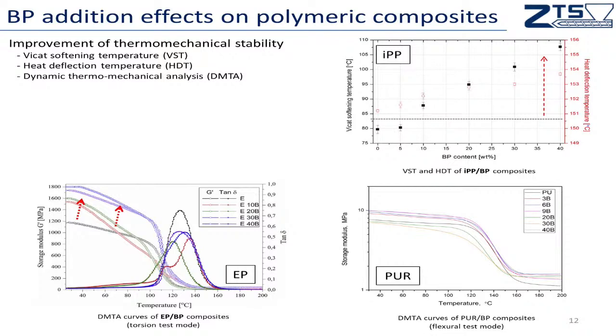The same phenomenon can be observed for the epoxy composites shown in the left bottom part of the slide. So we can see here the DMA curves of the epoxy resin composites. In the case of the highly porous structures of the polyurethane, the storage modulus, so the stiffness modulus, was improved by incorporation of the fillers. So for all materials, this is the property that will always change, and the same phenomenon can be achieved by using basalt fibers.